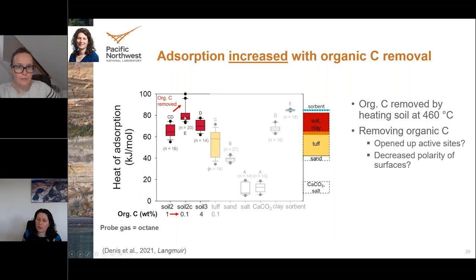And so on this plot, I've highlighted soil 2, which starts with 1% carbon, and then by heating it at 460 degrees Celsius, you can remove most of the organic matter. And then we went back and measured that same sample on the inverse GC. So we went from 1% organic carbon to 0.1%. And then in terms of how that affected the heat absorption, the removal of organic carbon actually increased absorption. So now the octane was absorbed greater onto the material. And that's actually something I wasn't expecting.